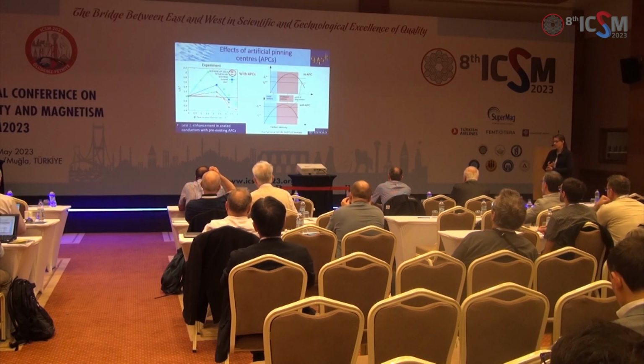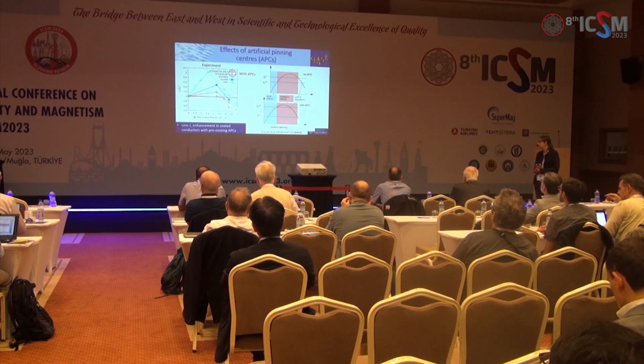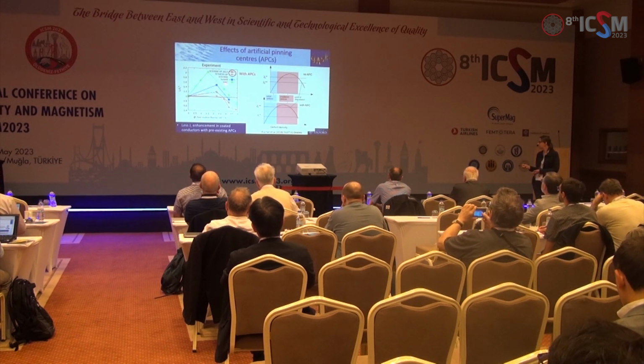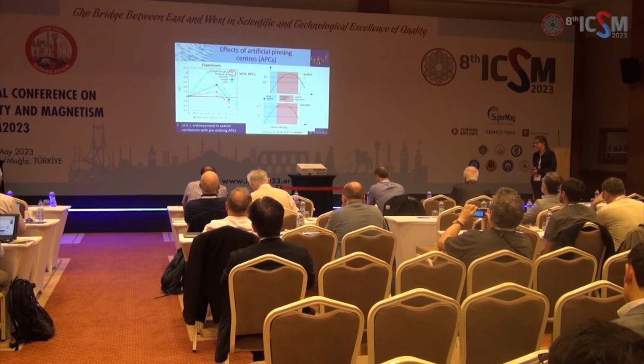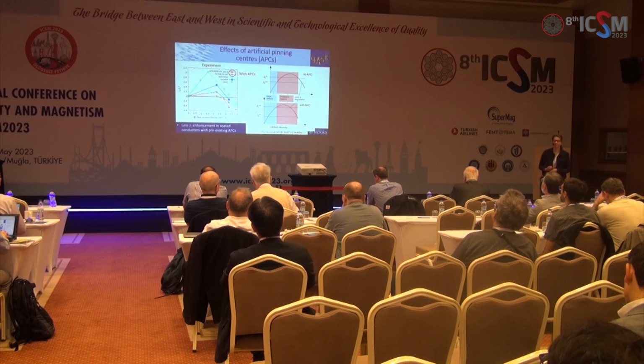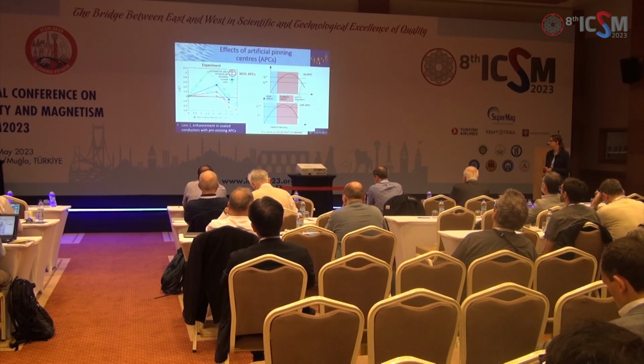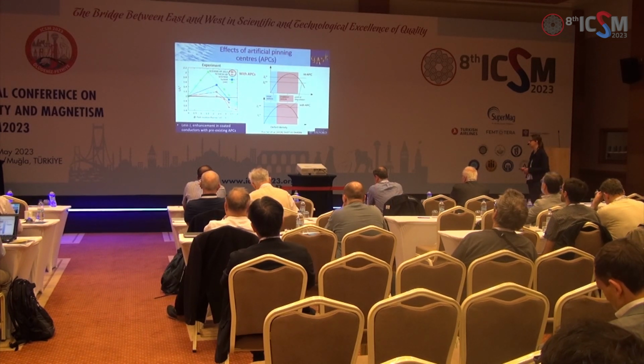So what's the effect of the microstructure of the coated conductors? Well, if you look back at this plot, there are different kinds of coated conductors in here, and the two lines in red and orange have artificial pinning centres, which are things like barium zirconate nanorods that have been deliberately added into the structure. You'll see that the enhancement you get in IC is not as good when you've got these advanced pinning centres already in the tape.